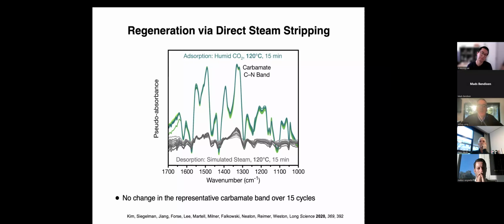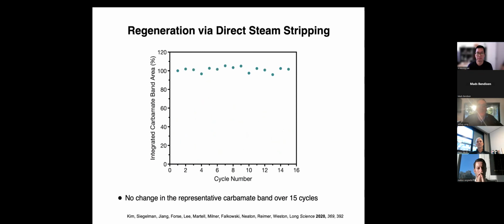And so you could actually use low heat steam, low quality steam for electricity production, even as low as 110 degrees and lower to remove the CO2 from such an adsorbent. And that can cycle. It's challenging to do these cycles, but we don't see loss of capacity here as we cycle CO2 and strip it out with direct steam contact.